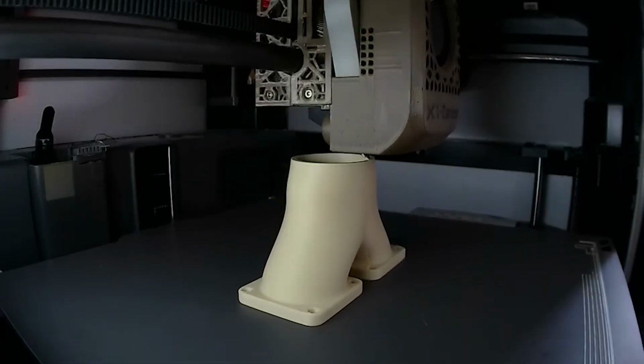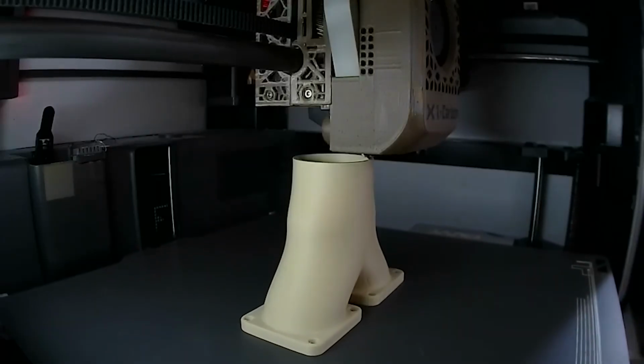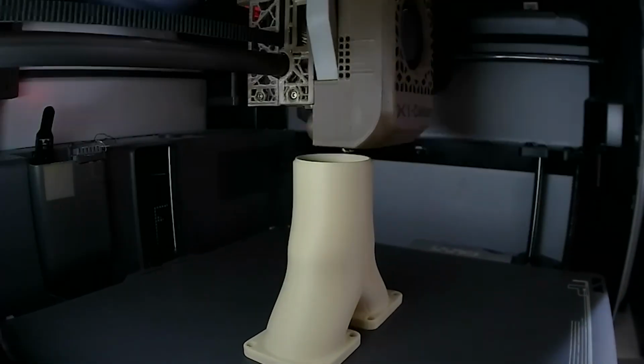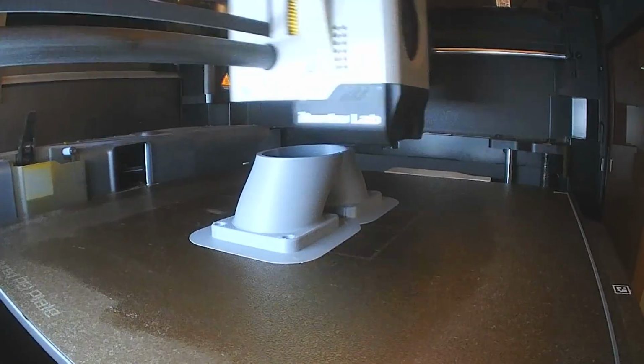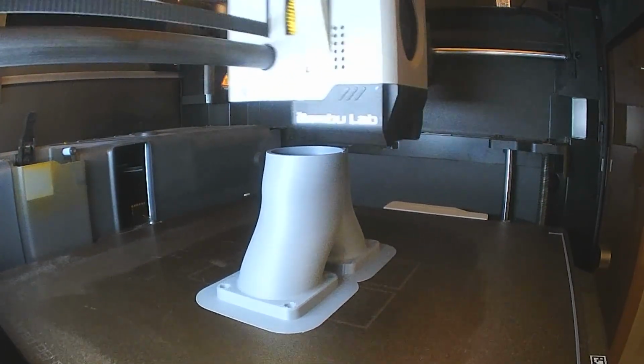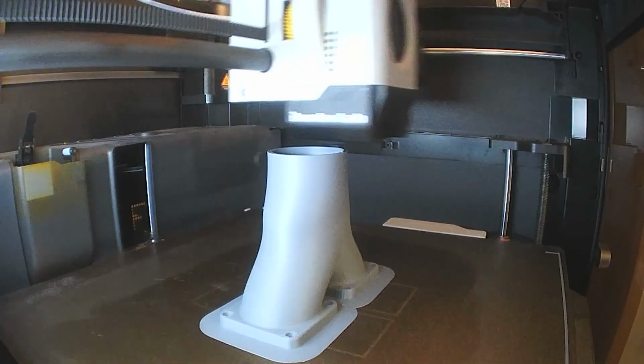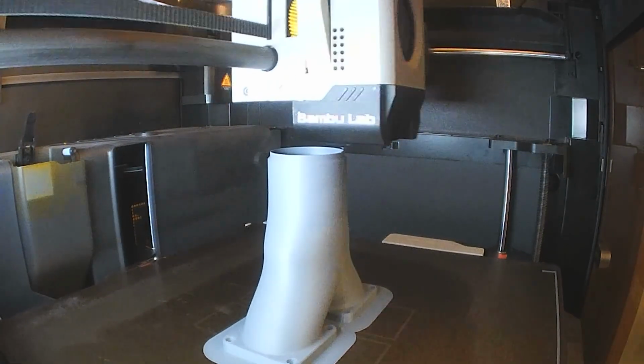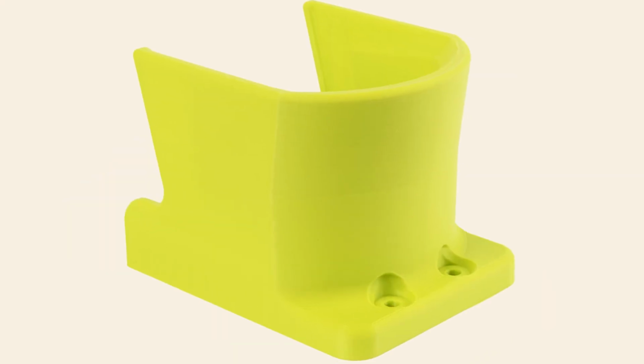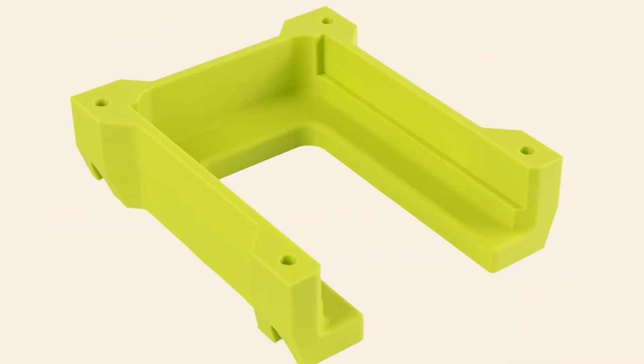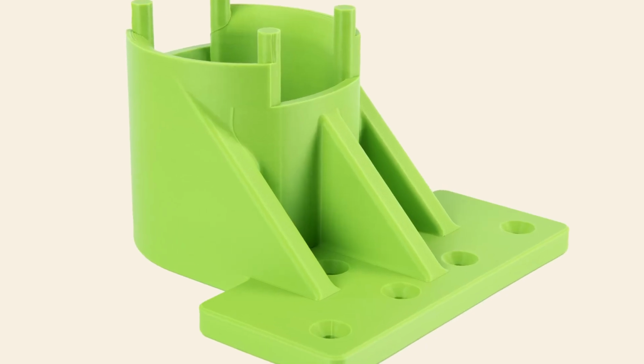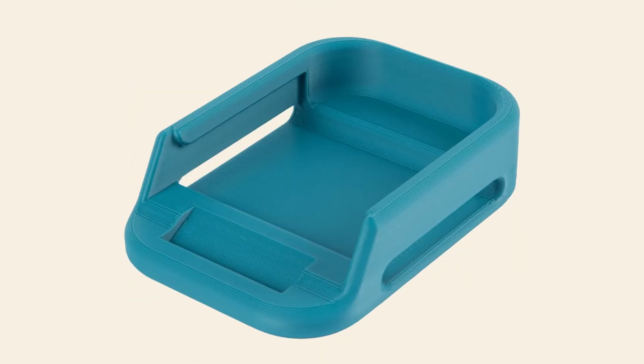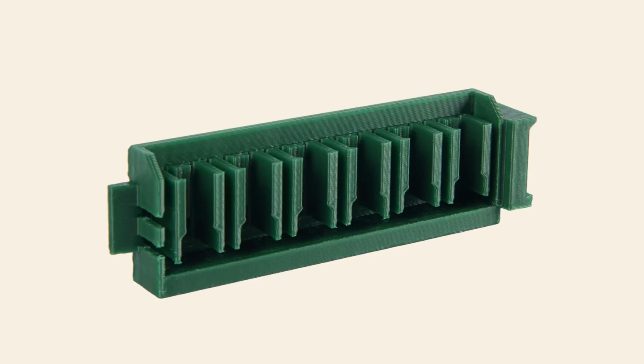However, if you are using a PEI build plate or another surface, we recommend applying additional adhesives such as Dimafix, 3DLAC, or Magigoo. Always clean the bed thoroughly before applying any adhesive to remove dust and grease. Warping. With larger models and sharp corners, slight warping may occur. Always use a brim, minimum 5 mm, to improve adhesion and stabilize the first layers. Cooling 80 to 100% depending on the model geometry. On printers with an enclosed chamber, better results can often be achieved with the doors kept slightly open.